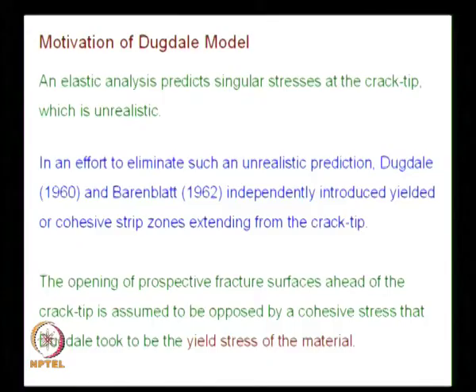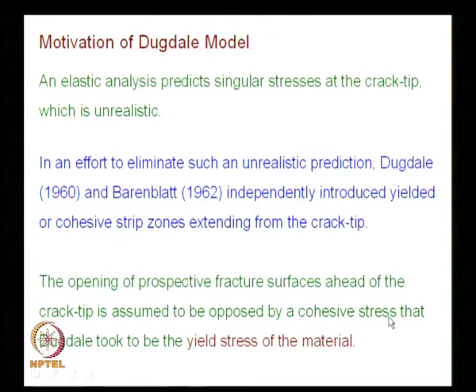You will have to keep in mind these are all models. People were attempting to solve a very complex problem, so they proposed approaches from their understanding. The opening of prospective fracture surfaces ahead of the crack tip is assumed to be opposed by a cohesive stress. Dugdale took that stress to be the yield stress of the material — it is essentially an assumption.